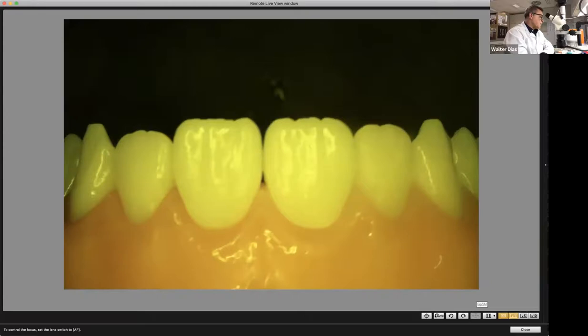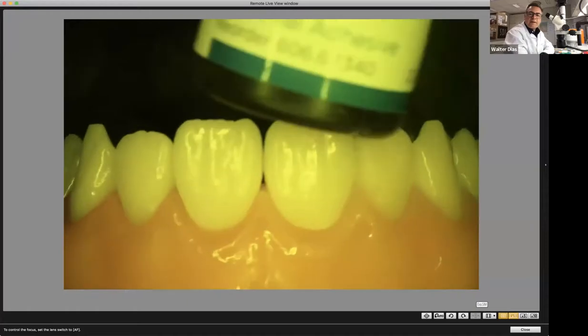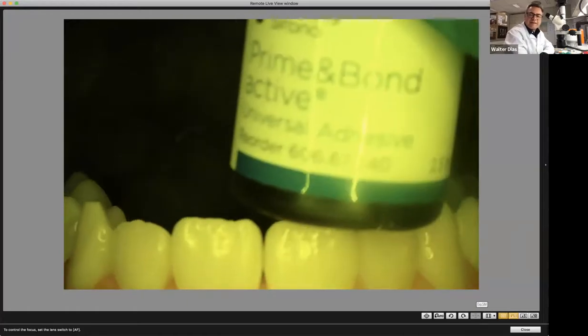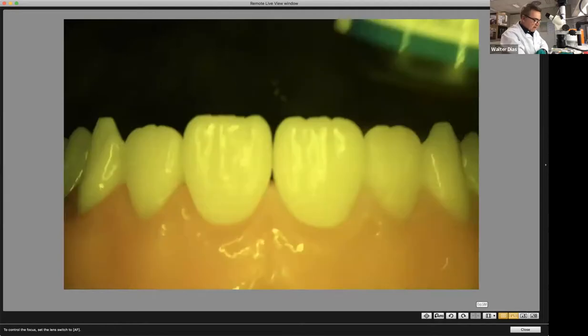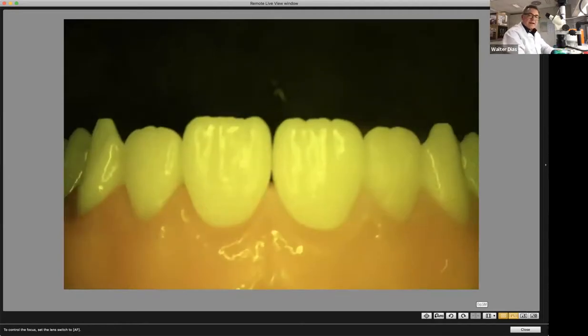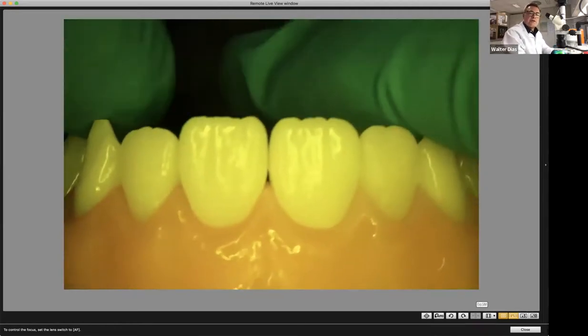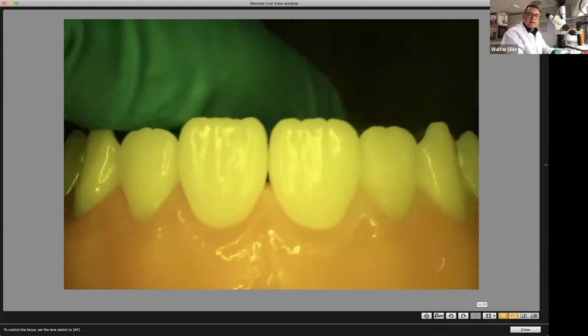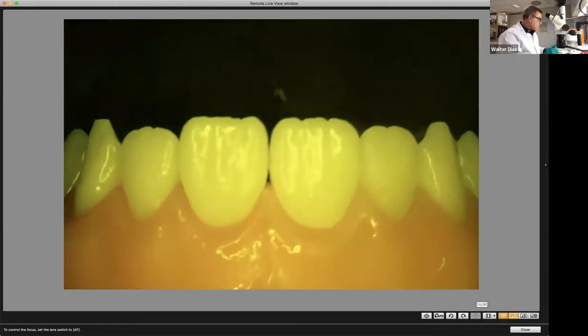In this case here, we're going to use Calibra, and the adhesive is going to be Prime Bond NT. And if you read the instructions, what it says there is that you should pre-cure the adhesive because this provides you a very thin adhesive layer. So you can pre-cure the adhesive. Very well.